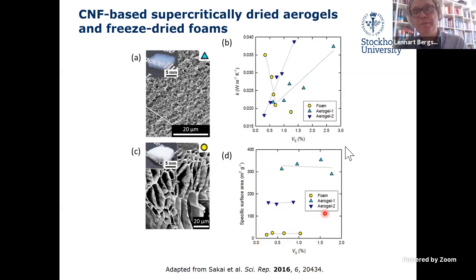And if you compare the specific surface areas here, you see it's a major difference - the supercritically dried aerogels have much higher surface areas. So just from simple estimates, you would expect these materials to have a lower thermal conductivity than the foams, but that's not the case.